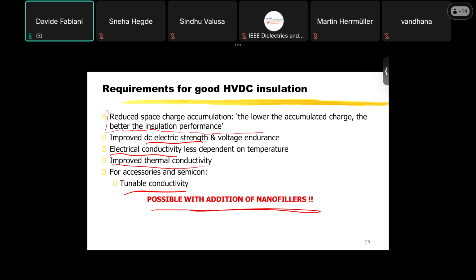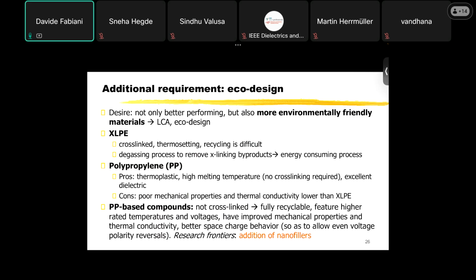There are also some additional requirements which came out very recently. The desire now is having not only better performing material, but also more environmentally friendly materials. This is due to the fact that cable manufacturers have to do the so-called life cycle assessment and eco-design of their equipment. So the use of XLPE, that is now the benchmark insulation that is used everywhere. The problem is that XLPE is quite difficult to recycle because it's a cross-linked thermosetting material. And also, the degassing process that is necessary to remove the cross-linking byproducts is a very energy consuming process.